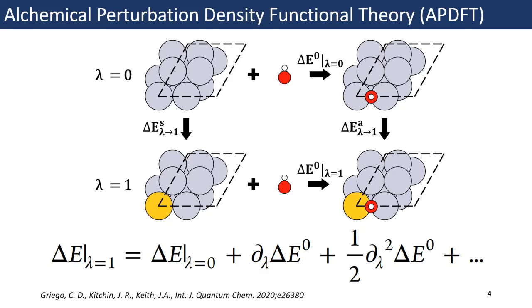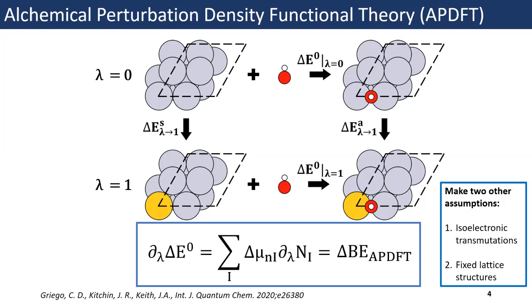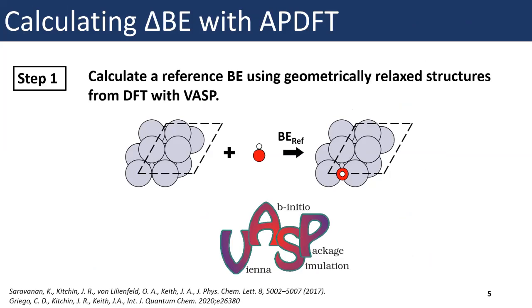We're only considering first-order approximations, so we can reduce all higher-order terms, and we're left with this first-order derivative, which is a function of the sum of the difference in electrostatic potentials based on the adsorption μ, which also depends on the variation of nuclear charge caused by the perturbation ΔZ. With this expression, we can calculate the binding energy change by making two assumptions: first, our transmutations are done isoelectronically so that the number of electrons is fixed, and second, the positions of atoms are fixed after these changes.